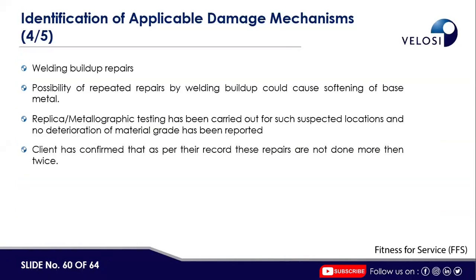Welding build-up repairs are done, which could be a problem if they are done repeatedly. The possibility of repeated repair by welding build-up could cause softening of the base metal. Replica metallography testing has been carried out for such suspected locations, and no deterioration of the material grade has been reported. The client has confirmed that, as per their records, these repairs have not been done more than twice.